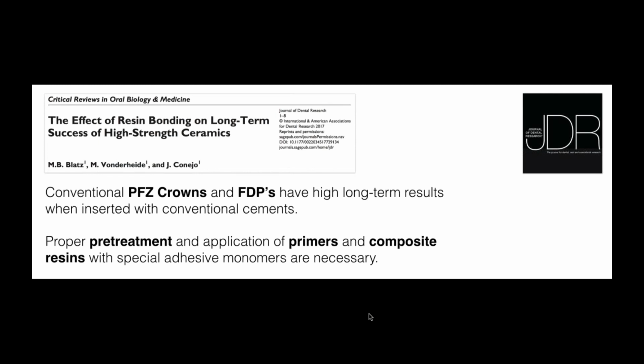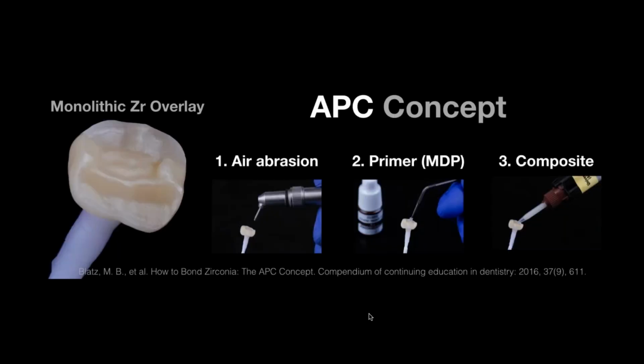So this was a publication we did on the effect of actually bonding to zirconia. If we have a conventional preparation design for porcelain fused to zirconia crowns or monolithic zirconia or fixed dental prosthesis, we can use conventional cements because we have retention and resistance form. But if we want to start using zirconia in a less invasive approach, then we need to use a specific pre-treatment protocol and specific primers that are not exactly the same that we've been talking through today when we discuss feldspathic ceramics, hybrid ceramics, or silicate ceramics. And this is called the APC concept.